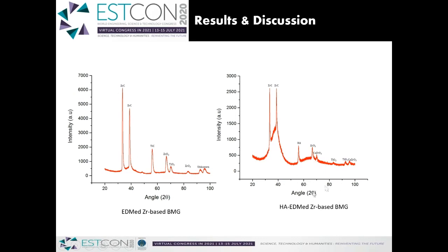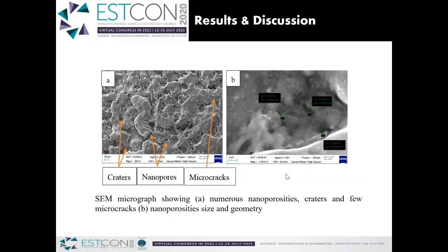While the HAEDM XRD depicts the presence of some HA on the surface, and also some calcium-based zirconium-based oxide. The calcium might be from the HA powder, which is added into the dielectric fluid. And although there are some sharp peaks, the amorphous nature is much higher than the crystalline peaks.